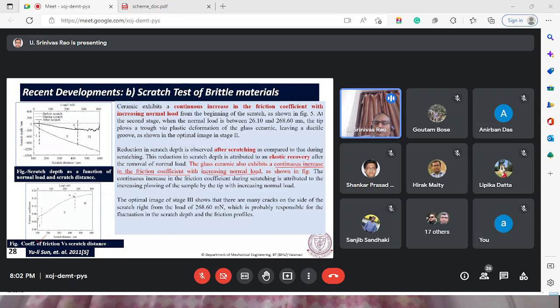Okay. So this makes for increasing ploughing of the sample by the tip with increasing normal load. And then when the ductile and brittle transition happens, a lot of cracks are happening, and that makes the scratch depth also fluctuate.